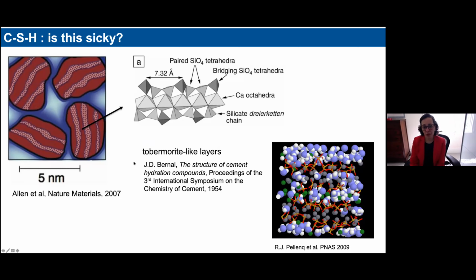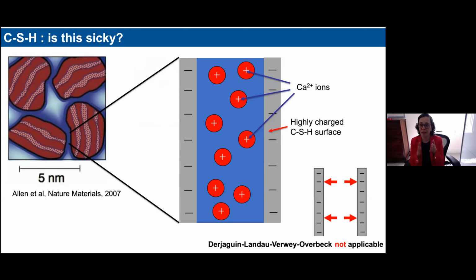But in the end, the cohesiveness of the material comes from the fact that the surfaces of the nanoparticles are very sticky with each other, and they are immersed in water and the ions that are continuously produced by the dissolution of the grains. So if we look at what happens between two nanoparticles, the surfaces of the nanoparticles are negatively charged, and the surface charge evolves as cement hydration proceeds due to the underlying chemistry. And so you have these negatively charged surfaces with counter ions in between, which are mainly calcium ions, and so you basically have like-charge attraction.